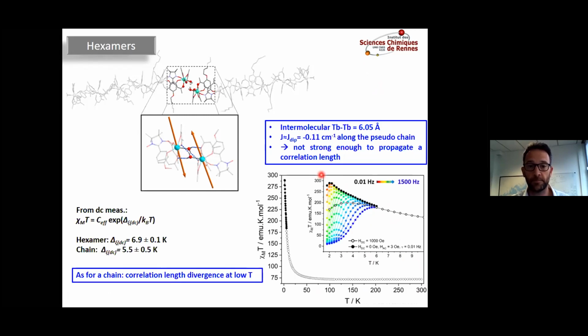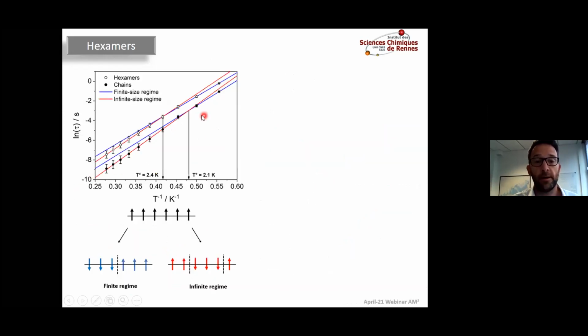And so you can see a chain-like behavior, but on a finite molecule, with correlation length data that are similar, a little higher than what we observe on the chain. So when you compare the hexamers and chains, hexamers actually behave a little bit better. You can even see two regimes on your system. So it means that the hexamers are big enough, because the correlation length is small enough, to see two different types of nucleation: the one that starts from the middle of the hexamer, so an infinite regime, and the one that starts from an edge of the hexamer.